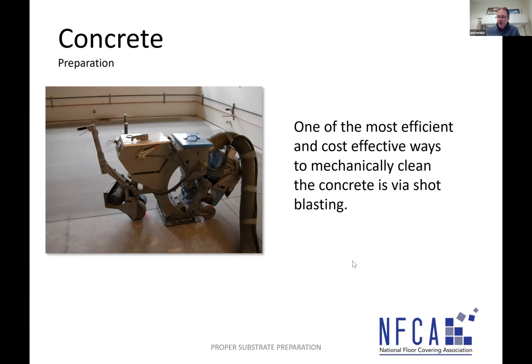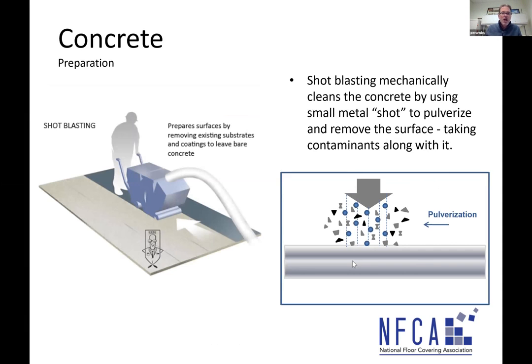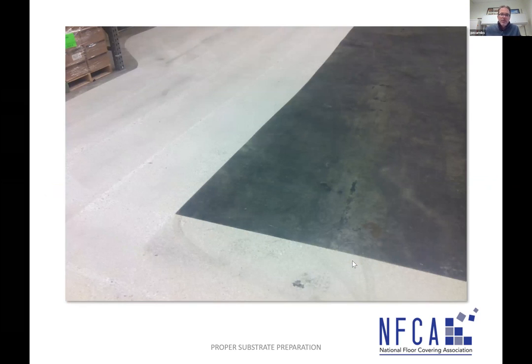It's a self-contained machine that has a motor and a wheel that throws a steel shot at the floor at a very high velocity, and it works on impact resistance. The steel shot hits the concrete and pulverizes the surface, taking the contaminants along with it. These machines have large vacuums with HEPA filters that pull the dust and debris off, but the shot's too heavy, so it gets recirculated. It's a continuous process of blasting that surface with this steel shot, leaving a very clean surface behind. In a couple of pictures here, you can see the light whitish look of that concrete. It has a little bit of a texture to it, but it's certainly clean, and that's the result of shot blasting.